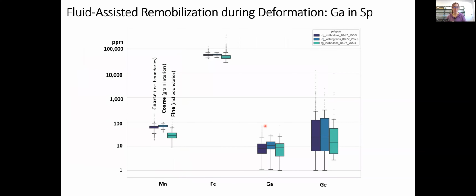And here we can compare those compositions. So we've got composition on the y-axis, concentration, with a log scale, and then different elements shown along the x-axis. And each of these box plots with a different color is for a different textural group. So the bright green is the fine-grained recrystallized sphalerite, and then the darker ones are our coarse-grained sphalerite.